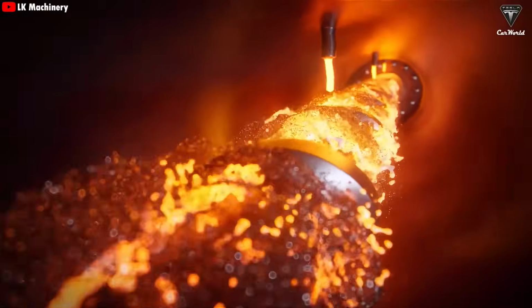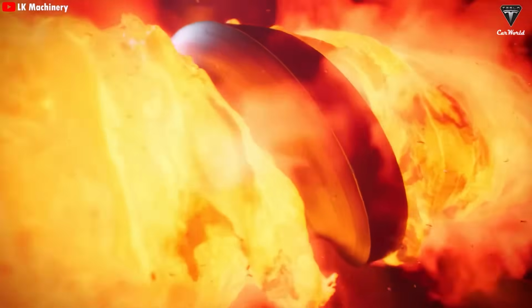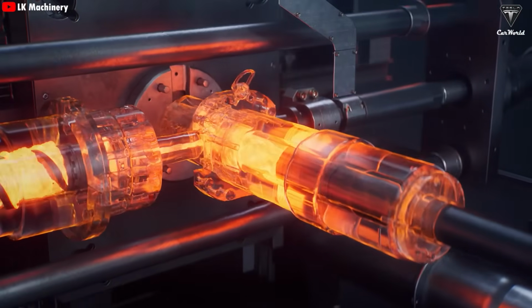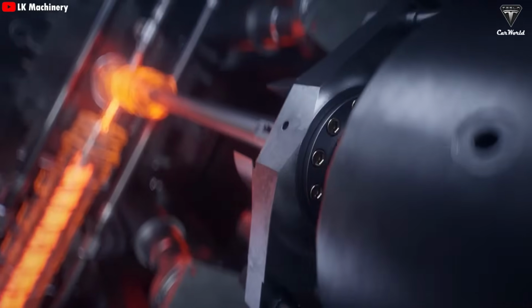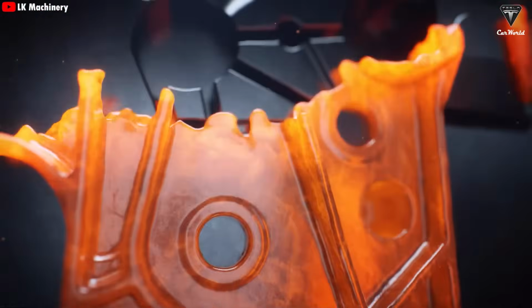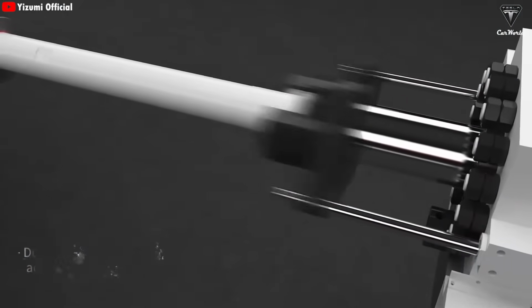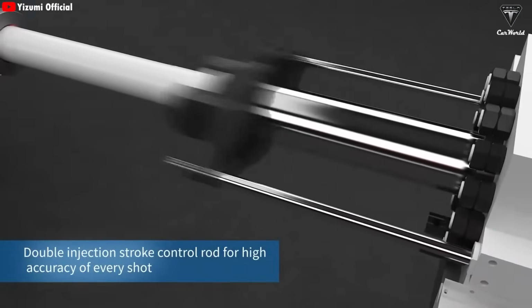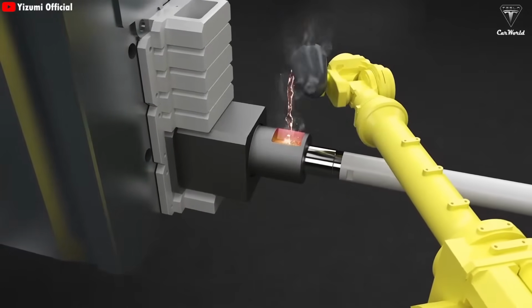Due to its enormous size and power, this press demands extremely tight control at every stage. One of the biggest challenges is that the molten aluminum must travel a longer distance than in smaller machines, increasing the risk of defects during casting. If the molten aluminum is injected into the mold too quickly, there's a high risk of air bubbles forming, which would weaken the final part's strength and durability.